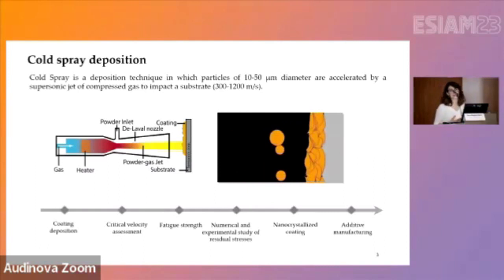The main, let's say, intrinsic characteristic of cold spray is that you can spray almost any metallic material mixed with each other, or also mixed with ceramic materials at temperatures that are much lower than the melting temperature of any material that is involved in the process. So that would give us a lot of flexibility in terms of selection of the material, mixing different materials, using materials that are oxygen sensitive or temperature sensitive.